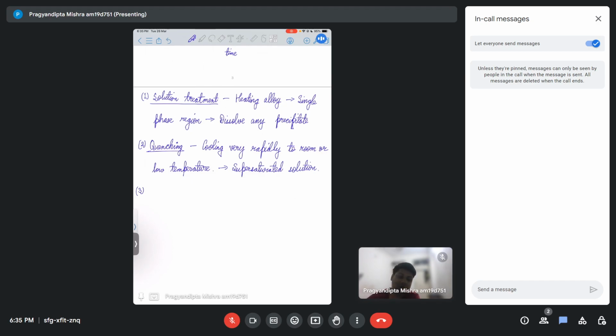Finally, you will again heat it to a little bit higher temperature and then hold it there for sufficient time so that precipitates can be formed. This process is known as aging. So you're heating to a temperature and then holding it there, which will result in the formation of precipitates.